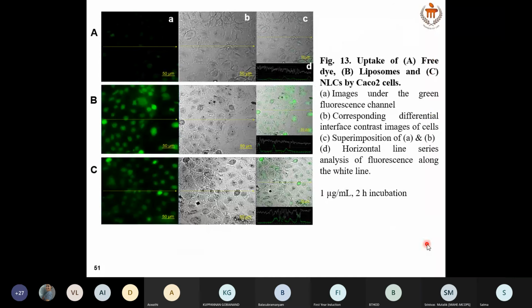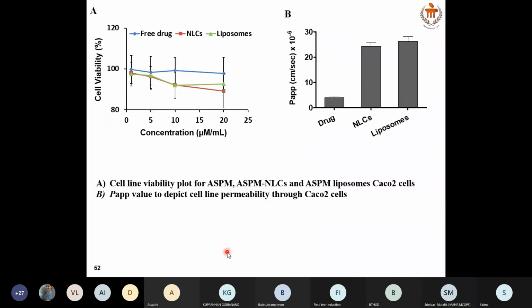Then uptake of free dye, that was FITC, then liposomes and NLCs was carried out in CACO2 cells. And here you can easily make out that the NLCs as well as liposomes were better taken up by the cells. Then cell line viability plot for ASPM, ASPM NLC, and ASPM liposomes in CACO2 cells, where the toxicity was not great. They were less toxic, meaning more than around 90% of the cells were viable.